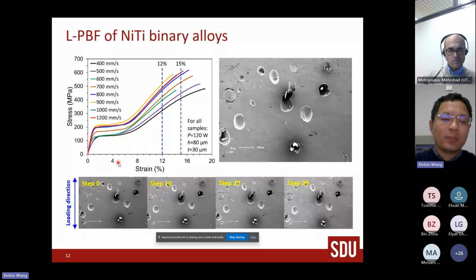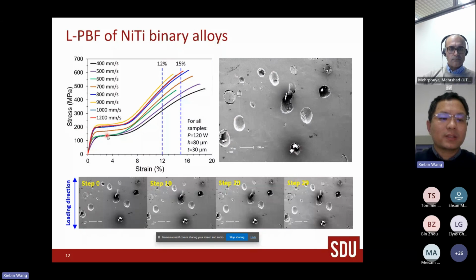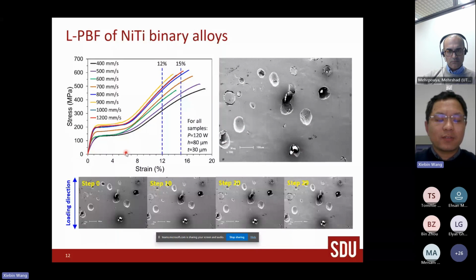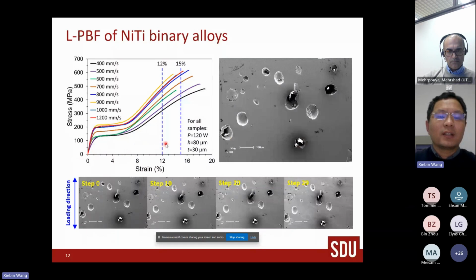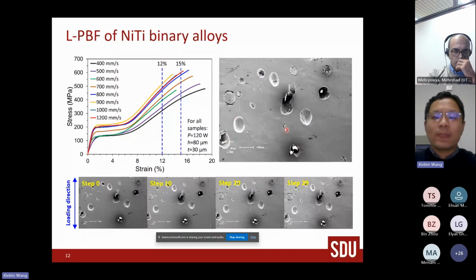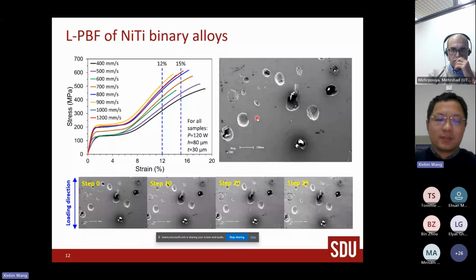But the reason for this phenomenon is very simple. If you look at this stress strain curve, there's a plateau at a very low stress level, below 200 megapascal, or even at 100 megapascal. At such a low stress level, the sample can deform like 6%. So it means at a very low stress level the sample shows a plateau, and at this plateau the pores don't break, and then it gives you a high ductility.